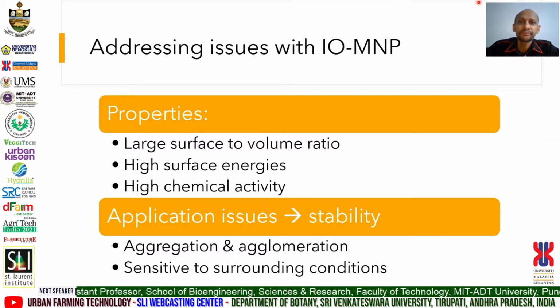As such, iron oxide magnetic nanoparticles tend to aggregate to minimize the surface energies when dispersed in solutions, also sensitive to surroundings conditions like acidity. Competitive adsorption due to self-aggregation of iron oxide nanoparticles cause colloidal instability.